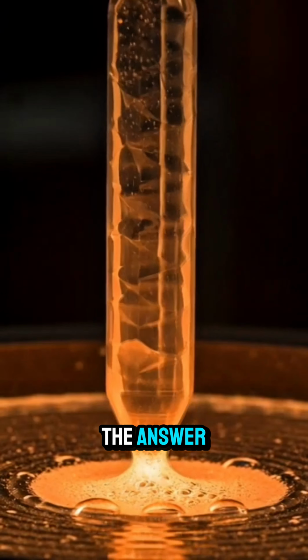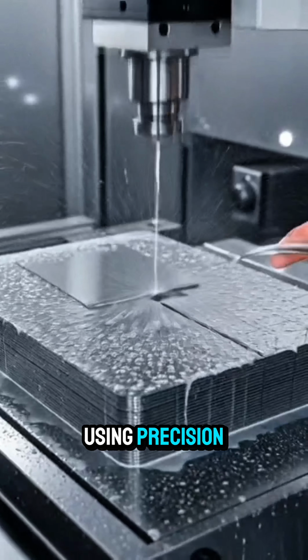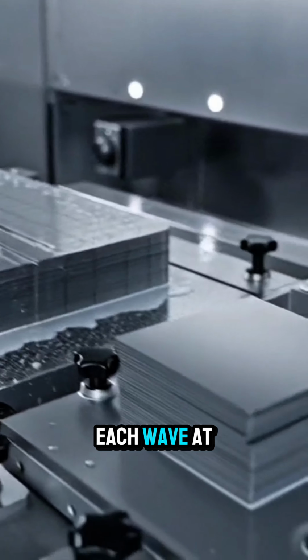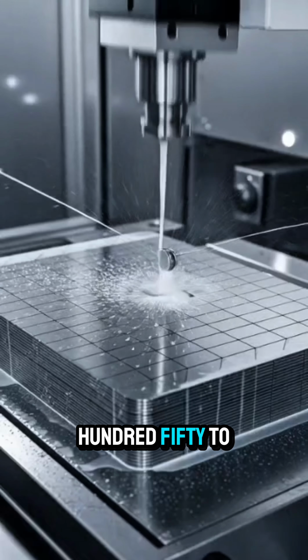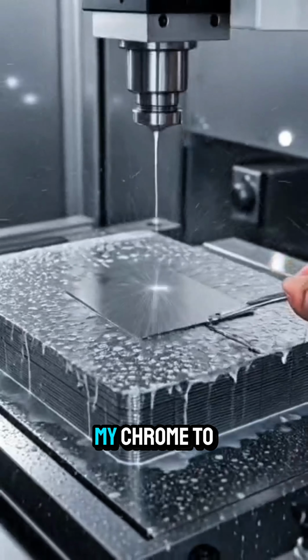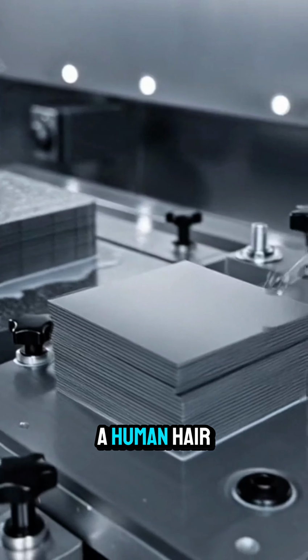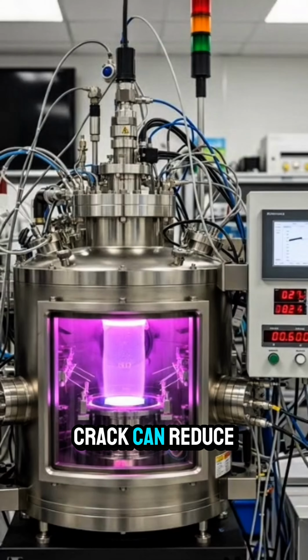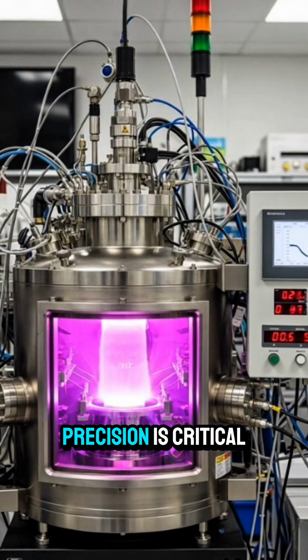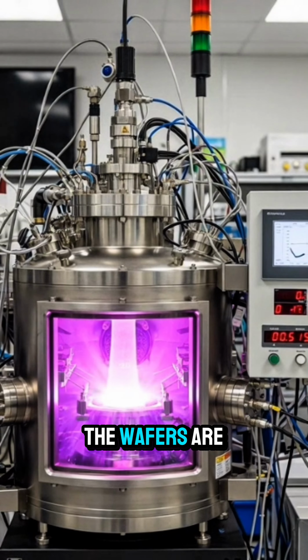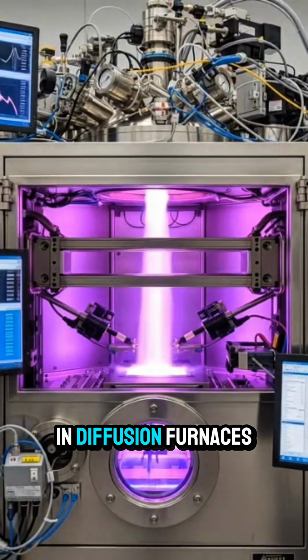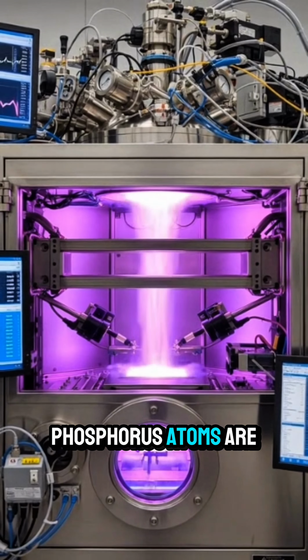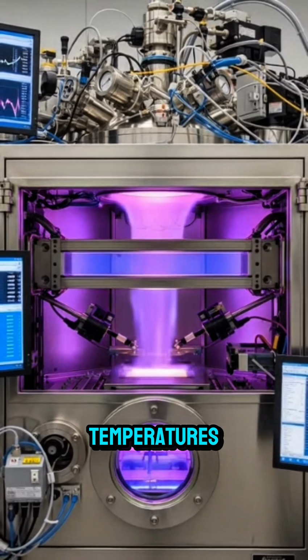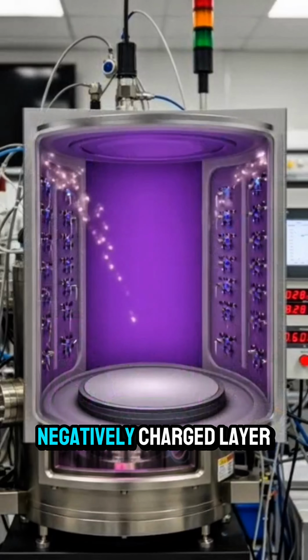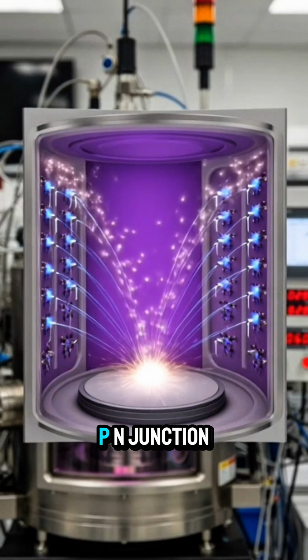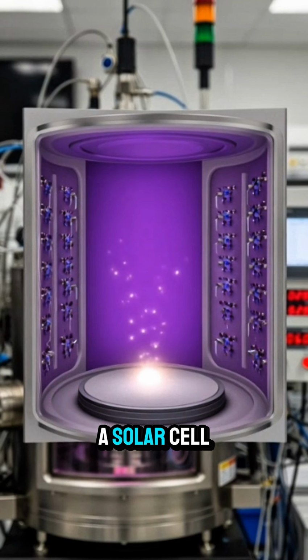The ingot is then squared and sliced using precision diamond wire saws. Each wafer is just 150 to 180 micrometers thick, thinner than a human hair. Even a small crack can reduce efficiency. Precision is critical. The wafers are cleaned and placed in diffusion furnaces. Phosphorus atoms are introduced at high temperatures, forming a thin negatively charged layer. This creates a p-n junction, the heart of a solar cell.